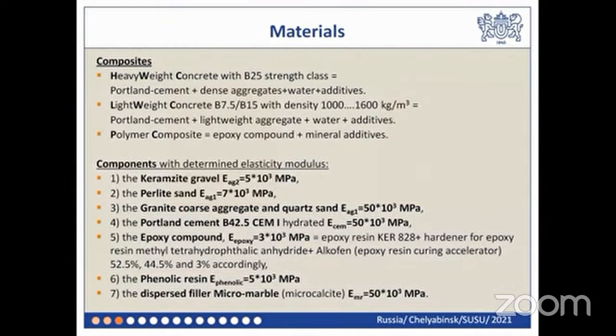Basic compositions for elasticity research were heavyweight and lightweight concretes and cured epoxy resin. These compositions were chosen because of their principal structural and deformability difference. To determine the actual concrete elasticity modules in our experiment, we used local producers' materials with definite elasticity modules and presentation. The contents of various classes of mixture components are presented in the following tables.